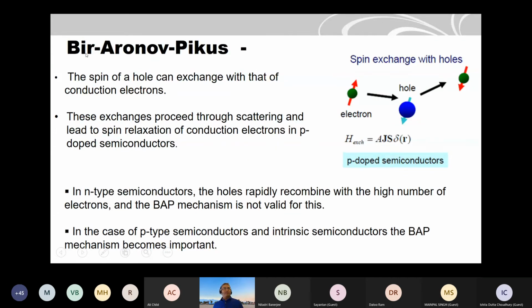Then there is another mechanism called Bir-Aronov-Pikus, which is actually due to electron-hole exchange interaction. In your material, there is always electron-hole recombination and creation going on. So you create electrons, and the electrons get trapped and get the holes. That is more active in p-type semiconductors because you have more holes. So in this case, you can consider that this mechanism can also flip the spin.